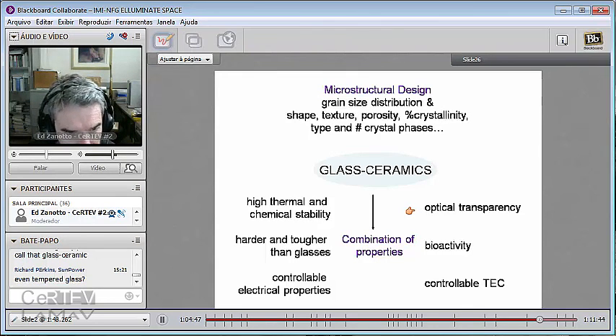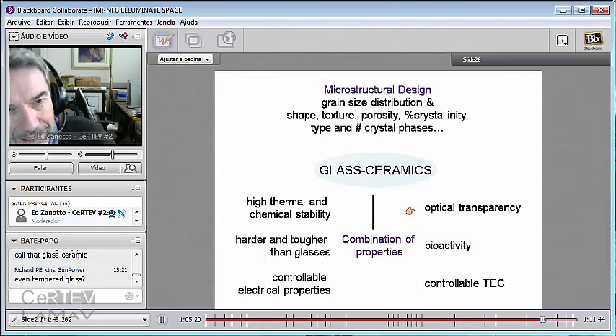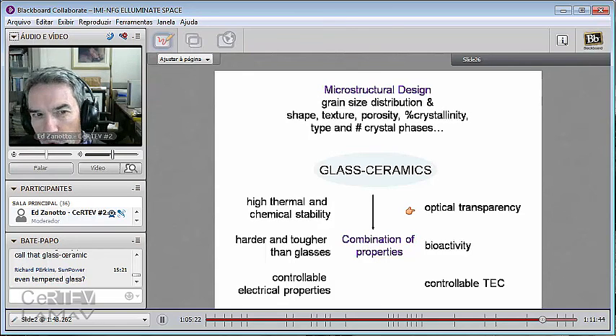Even tempered glass? Yes, Richard. Glass ceramics can be stronger, and they're definitely tougher than tempered glass. Tempered glass is not tougher. Tempered glasses, due to their residual stress fields, are stronger, but they're not tougher. Glass ceramics are tougher. Once a crack starts to propagate, they resist. There's an intrinsic resistance to crack propagation in glass ceramics.